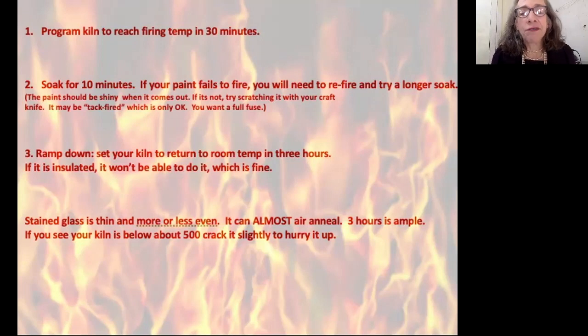And if it kind of comes off, you have tack fired it, in which case I think you should refire for a full fuse. So program the kiln to reach temp at 30 minutes, soak for 10 minutes, and then ramp down. You can set your kiln to return to room temperature in 3 hours. If it is insulated, it will not be able to do that, but that's fine. Stained glass is thin and it is more or less even. It can almost air anneal, so 3 hours is ample time.